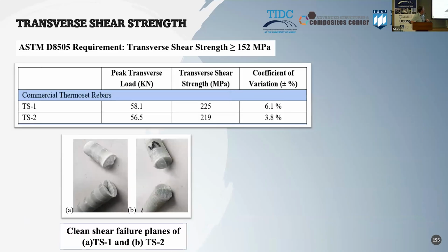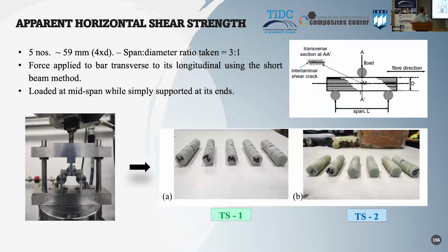Next one. We look at the values and we compare with the requirement for the standard. The standard requires 152 megapascals, and we're getting more than 200 here with both systems. Again, pass the mark. We look at the failure surfaces. This is very important, clear failures. Again, good failure in shear. Next.